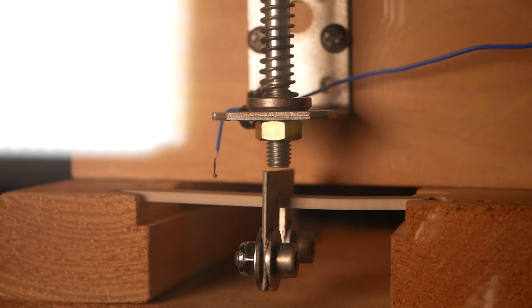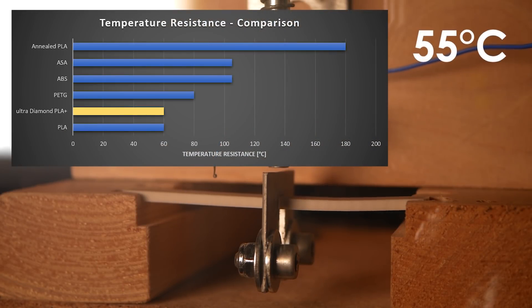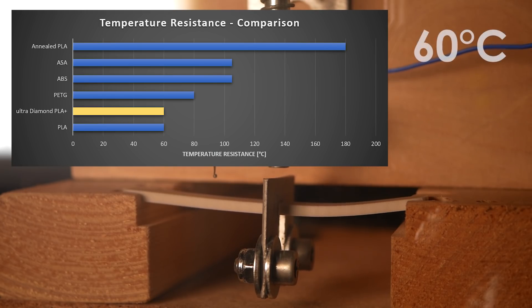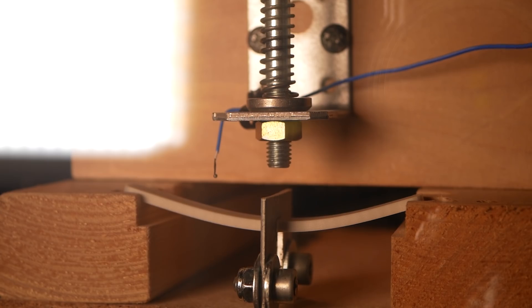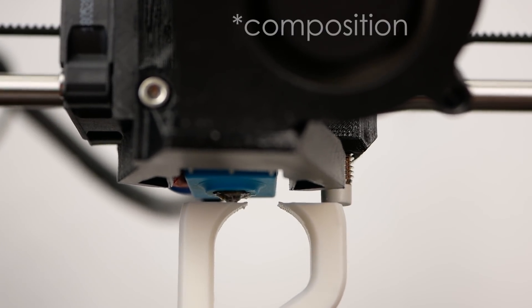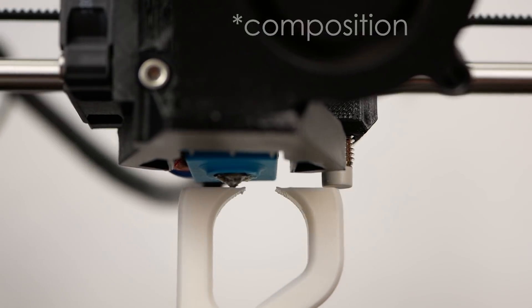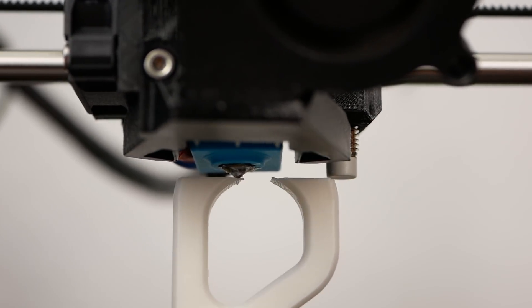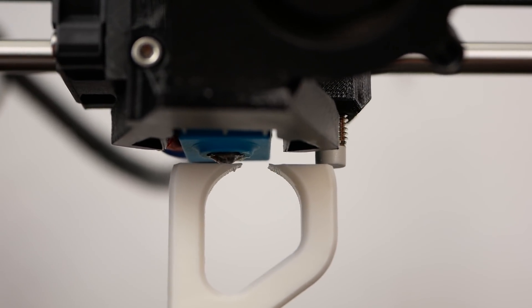Despite the bold claims at least my material already softened at 55 degrees celsius and then totally failed at 60 degrees celsius very similar to other PLA. This is where annealing comes into play. Ultradiamond PLA Plus uses a special composition of PLA that only minimally deforms during the annealing process so parts don't warp during that procedure.